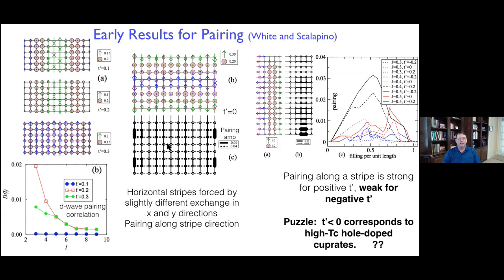And then we can make a different kind of measurement. The lower left was a pairing correlation. Here's a pairing susceptibility, where we put a pair field operator that creates or destroys a pair on the edges of the system, and then we measure the response. We only do it on these four bonds. We only put an applied field there. The thickness of the line shows the strength, and the dashed lines are opposite in sign to the solid lines. So this pattern clearly shows that it wants to be D-wave. And the response from applying this small field on the edge persists all the way through the system. So we're seeing a response to the pairing along this length of the stripe.